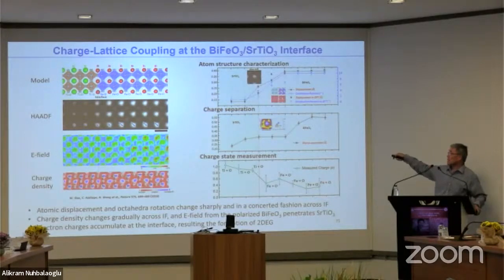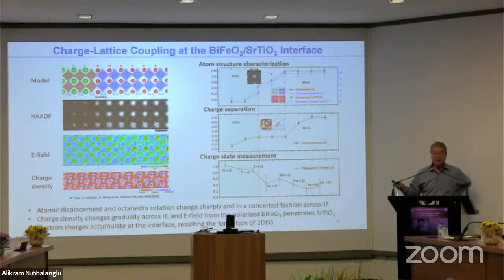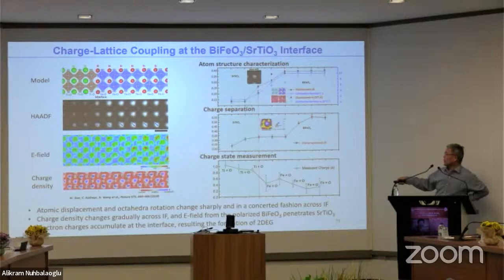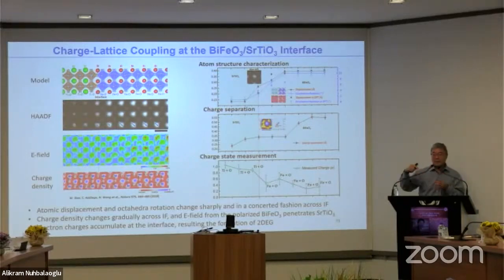Bismuth ferrite is ferroelectric, and therefore interfaces can be charged. This is the charge and electric field. This is the charge distribution. By analyzing the charge distribution, we can directly see the existence of a two-dimensional electron gas, because the polarization is pointing to the interface. With additional analysis, by looking at the position of each layer's anions and also the electronic charge distribution, you can see that the change of structure is much faster than the change of the electric property. The polarization will penetrate into the non-ferroelectric material, but the structural distortion is quite sharp. It's only 2 or 3 unit cells thick, but the polarization and charge will extend across about 5 or 6 unit cells. So this is one example.